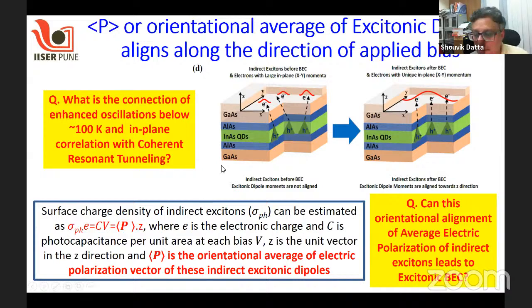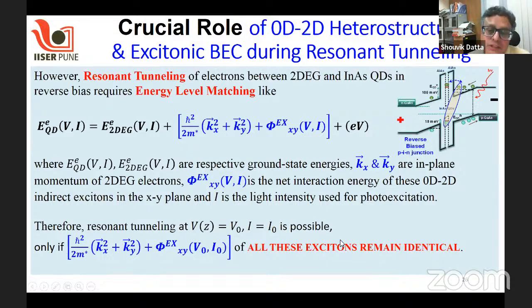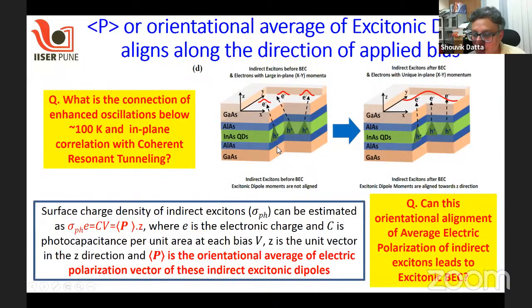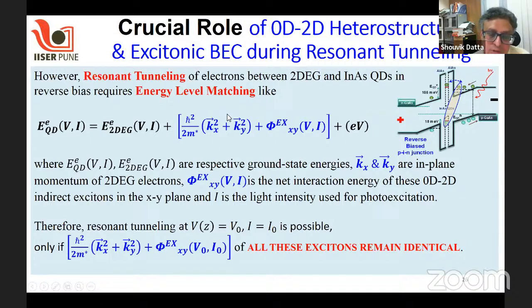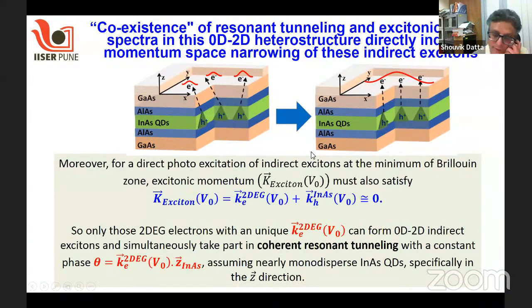So what is the connection between these? It seems that as the excitons form, if the negative quantum capacitance drives these excitonic systems towards aligning the average electric polarization along the direction of applied bias, there may be some localization of these electrons which may be driving the BEC. And because we are seeing very sharp oscillatory features in these photocapacitance measurements, it turns out that such localization of these electrons can only happen if we put some restrictions on the in-plane wave vectors or the kinetic energy of these electrons in the plane of the sample. And that can certainly point towards the fact that these electrons or excitons can go towards a state where the transverse component of their momentum can be severely restricted.